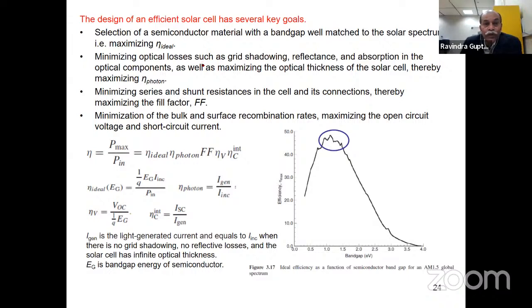Optical losses should be as little as possible, very, very low. So there should be no grid shadowing, no reflectance, no absorbance, and the optical thickness of the solar cell should be maximized. Another thing is the series resistance and shunt resistance should be low, and therefore the fill factor will be high. And minimizing the bulk and surface recombination rates will increase the open circuit voltage as well as short circuit current. So these are the parameters to improve the solar cell efficiency.